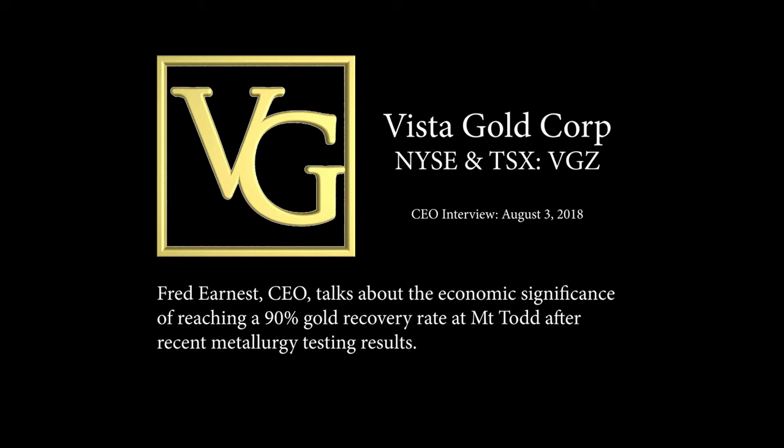Yeah, your cutoff's about 0.4. That's right. And so achieving this recovery with a low-grade sample is very exciting for us, because where we think we're at is we think that we have finally reached a grind size where we are achieving what's called a constant tail. That's one of the things that we're going to test and validate: as we grind and then leach higher grade ore samples, if we're able to achieve the same tail grade, somewhere between 0.06 and 0.07 grams per ton going out to the tailings impoundment facility, what that means is that as we process higher grade ore, the recovery goes up.